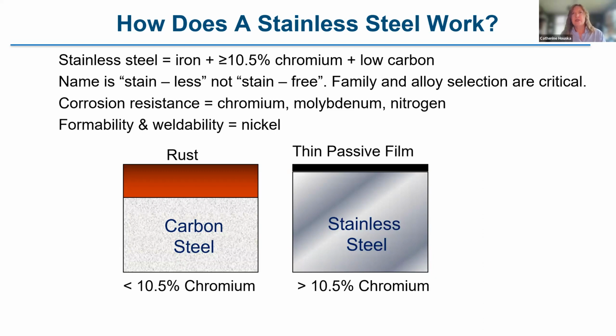When stainless steel is clean and exposed to oxygen, it will form a thin passive film. It's similar to the passive film that you might be familiar with on aluminum, for instance. And as long as that stainless steel is corrosion resistant enough for the service environment, then it will remain free of corrosion. But it is very important to select the alloy.